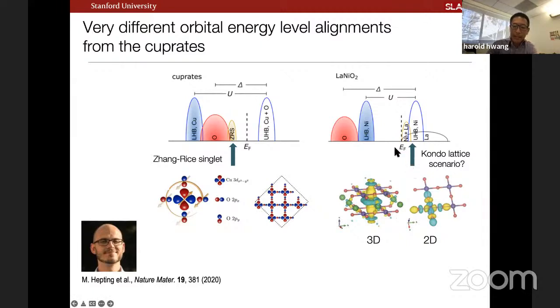In the nickelate case, the starting features are rather similar, but there's an additional ingredient. The first statement is that where things align look rather different. So the nickel 3D band is split, nominally similar to or above the oxygen states. And you're also kind of in the midst in the upper Hubbard band regime in a manifold of bands derived from the rare earth or lanthanide 5D electronic states. So if you dope in this system, you have an interesting additional degree of freedom.